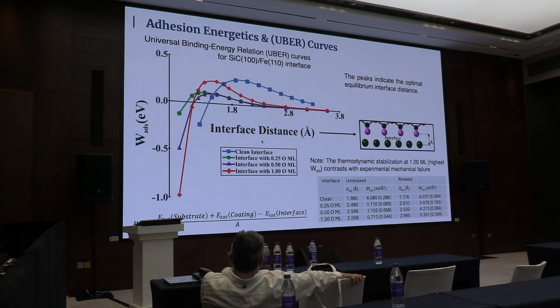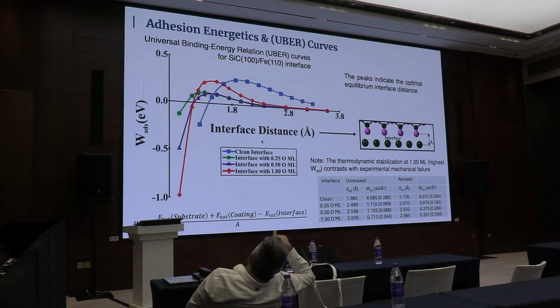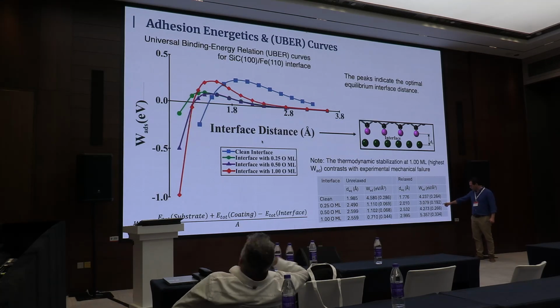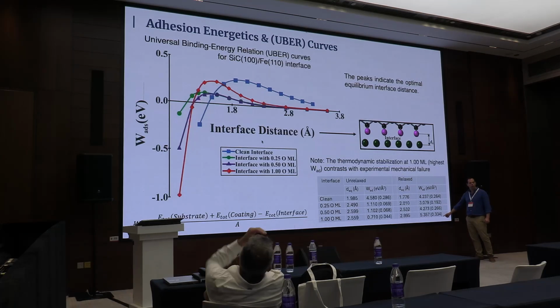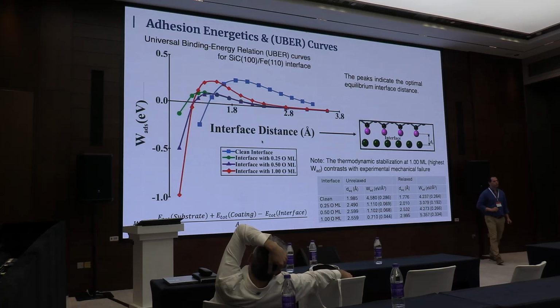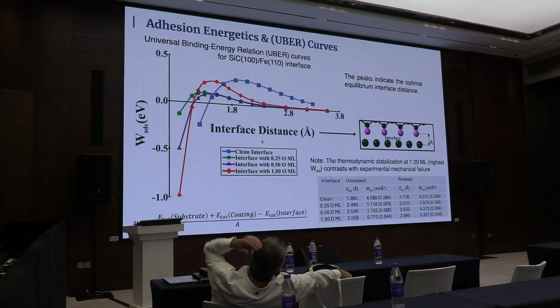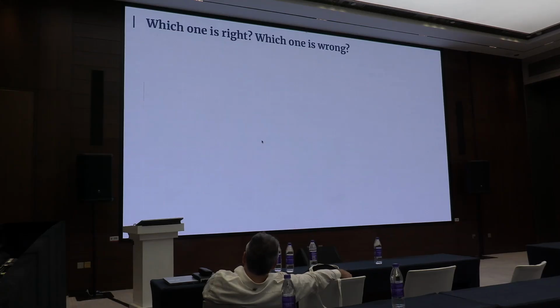So when we relax the system, we observe there is a lot of shift between the interlayer atoms, and when this happens the energy is good, but we can observe from this relaxed system that when we start to increase the concentration of oxygen, the value is higher than the first. It means that the system with oxygen is stronger to be taken apart than the system without oxygen. This is in contradiction, first of all, with Carlos's experiment. So, which is wrong?